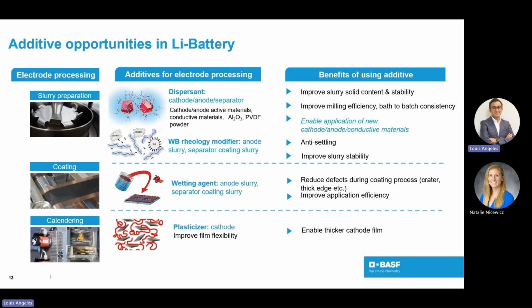Just as an example, in the electrode formulation, additives play a crucial role in the formulation of electrode materials for batteries. They are used to improve the performance and stability of the electrodes by enhancing the conductivity, optimizing the particle size distribution, controlling the porosity, and facilitating the interaction between active materials and the electrolyte. Our business has been focused to offer solutions to the slurry preparation of the cathode, anode, and separator components, in addition to the coating layer and calendaring process. Some of the benefits of using the additives portfolio are listed here on the right side of this slide. But it depends on how the battery technology is developed to really get the best performance of our products.